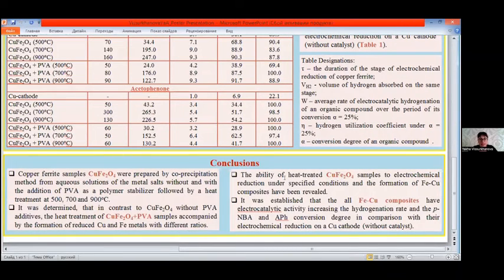The main conclusions are given at the end of the poster. Firstly, copper ferrite samples were prepared by co-precipitation method without and with the addition of polyvinyl alcohol. Secondly, the iron-copper catalysts were obtained during thermal and electrochemical reduction of copper ferrite samples. Thirdly, it was established that all iron-copper composites have good catalytic activity in the electrohydrogenation reaction of organic compounds. We are sure that the as-prepared iron-copper bimetal composites can also be used as catalysts in various electrocatalytic and catalytic processes of organic chemistry.